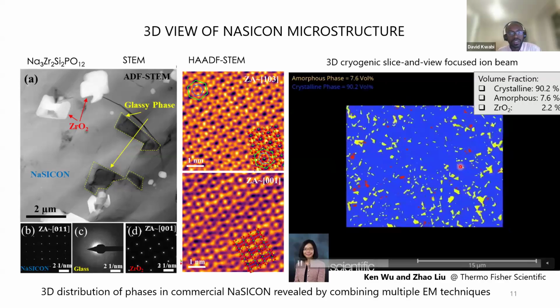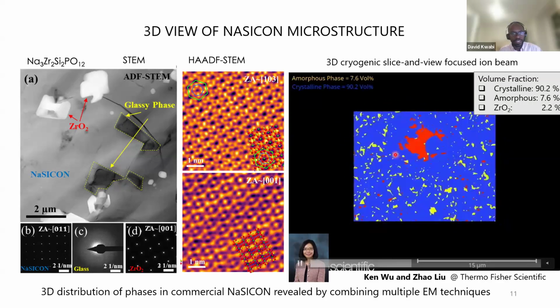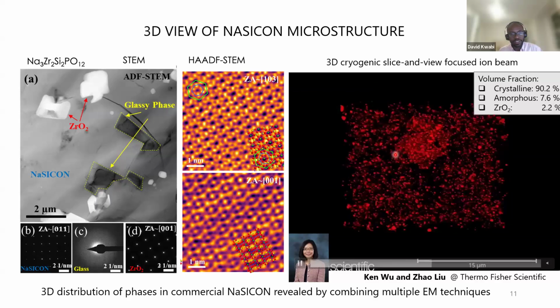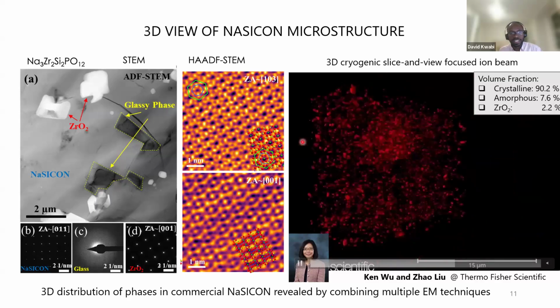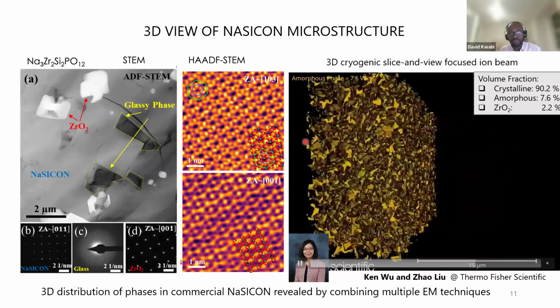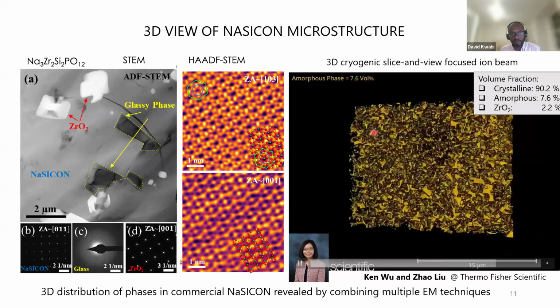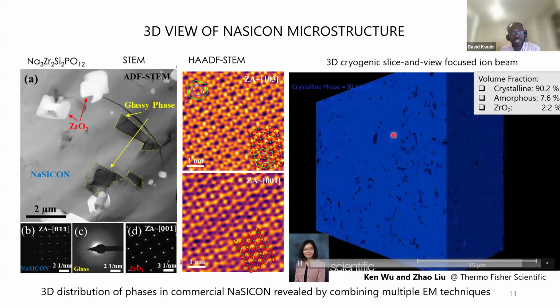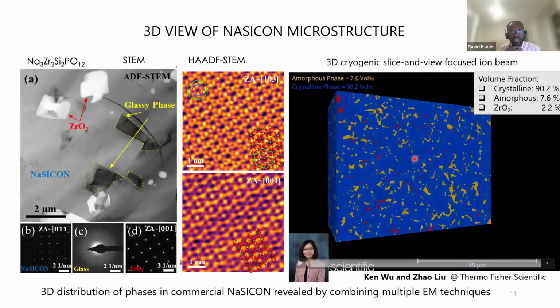Right? So we can see here that there's about 90% of the crystalline phase, about 7% of the amorphous phase, and about 2% of the zirconium oxide phase in the sample. And what's neat about this slice and view technique is that you can really nicely see how interconnected all these phases are within the microstructure of NaSICON that's made by using this conventional technique.